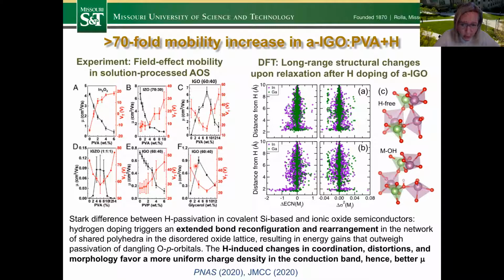What we found here from the theoretical calculations is again long-range structural changes upon relaxation after hydrogen is introduced into indium gallium oxide. Here I show the change in the effective coordination number, or the distortions of the metal atoms. Purple represents indium, green gallium atoms, shown as a function of the distance from the hydrogen. We can see significant changes, for example in the distortions of gallium, even up to 10 angstrom away from where the hydrogen is located.